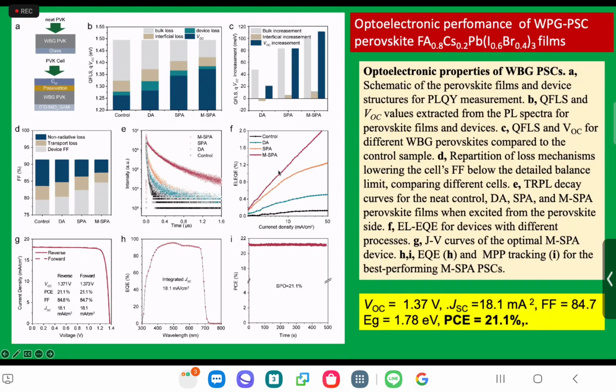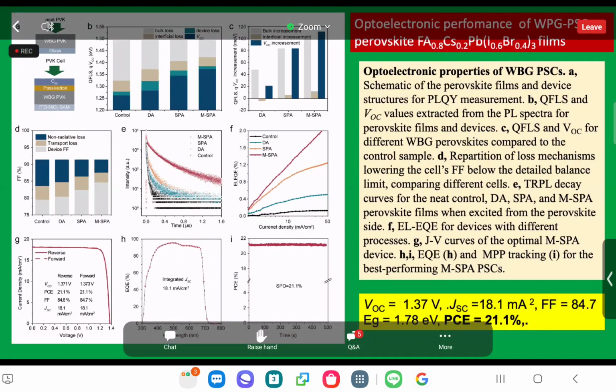And also, one critical thing is electroluminescence, external quantum efficiency. So you have to look at the point here on the x-axis, which is the short circuit current. Now that may be around here. So we're getting over 1%. Of course, one can get much better results with NIP, but I'm just telling you that for a PIN structure of this band gap, it looks good.